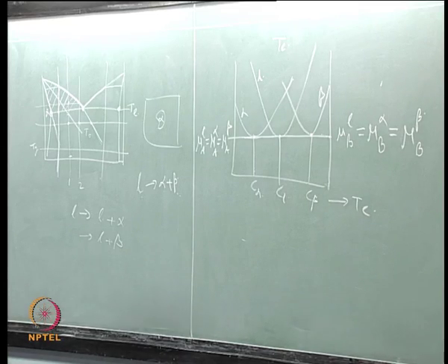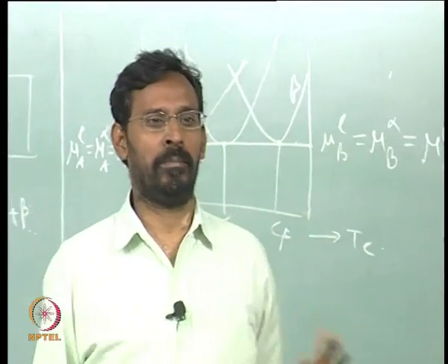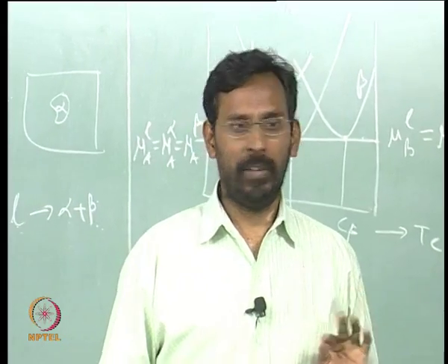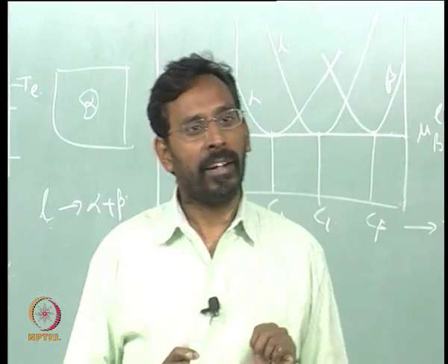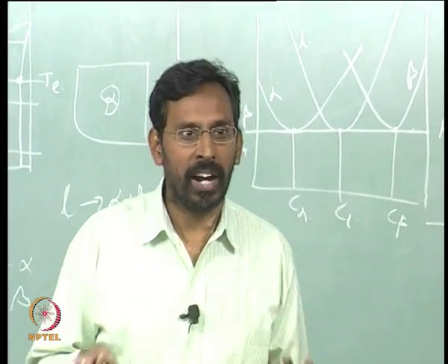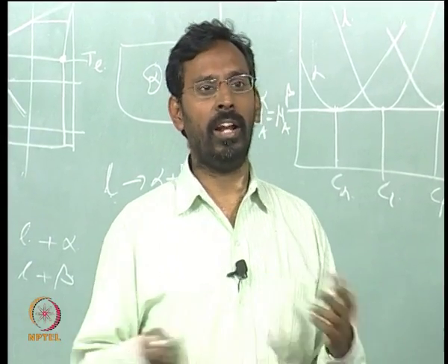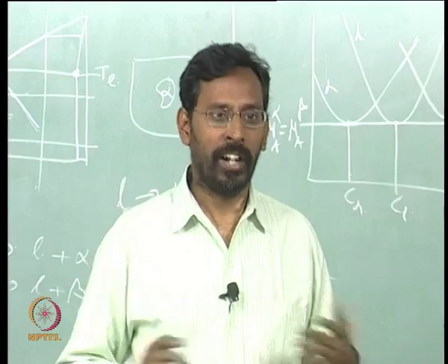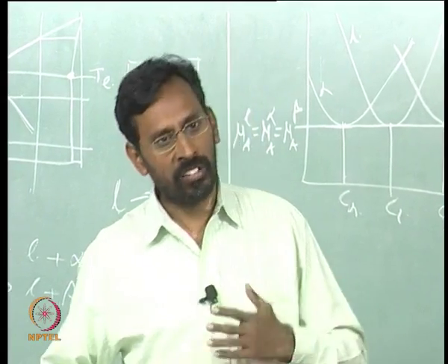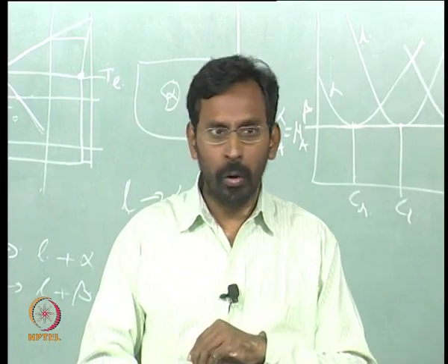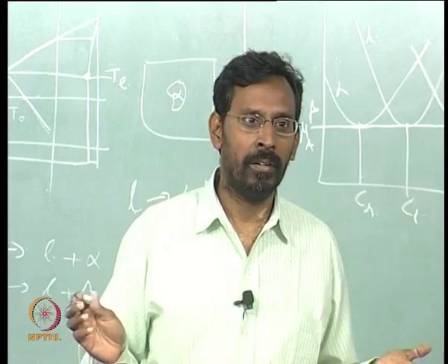Correct. See, the question is, whenever we talk of equilibrium, there is always something called local equilibrium, which has to be maintained, unless you are in such a highly non-equilibrium state that atoms cannot move at all, like a martensite transformation, a diffusionless transformation, or a liquid giving you a glass, where you are at such temperatures that no diffusion can occur, then local equilibrium fails.